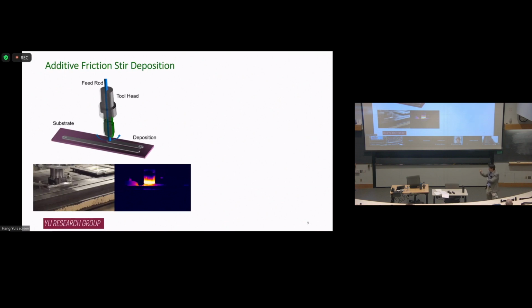So what's going on here is I have my feeder rod going through my print head. And during deposition, both the feeder rod and the print head rotate very fast. Usually we talk about a few hundred RPM. As the feeder rod gets into contact with the substrate, there will be frictional heating there. So the feeder material will get hot and soften. Then you apply compression, the material basically will yield and be extruded out to the side.